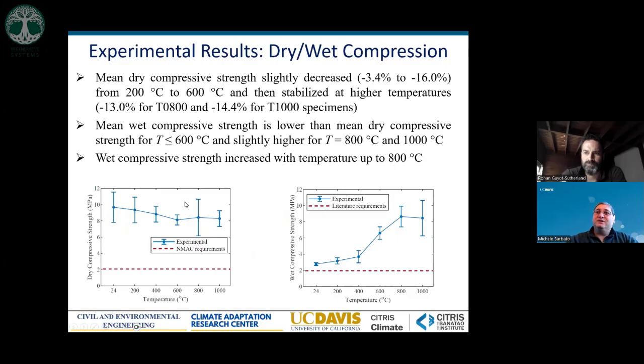In terms of dry and wet compression, there is a small reduction in compressive strength under dry conditions, which is actually statistically insignificant. So we cannot really state there is a reduction because statistically speaking, the difference is so small. So fundamentally, from a practical point of view, there is a maintenance of the dry compressive strength of the material across all of the temperatures that we have investigated.